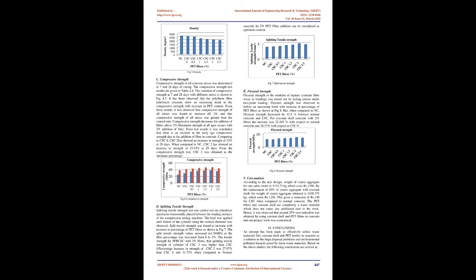Compressive strength. Compressive strength of all concrete mixes was determined at 7 and 28 days of curing. The compressive strength test results are given in Table 4.4. The variation of compressive strength at 7 and 28 days with different mixes is shown in Fig 4.5. It has been observed that the polythene fiber reinforced concrete shows an increasing trend in the compressive strength with increase in PET content. From these results, it was observed that compressive strength of all mixes was found to increase till 2% and that compressive strength of all mixes was greater than the control mix. Compressive strength decreases for addition of fibers above 2%. Maximum strength at all ages occurs with 2% addition of fiber.